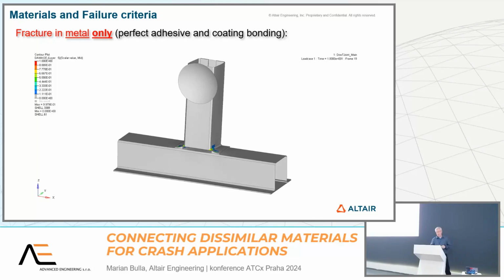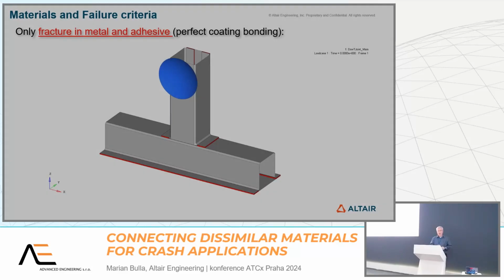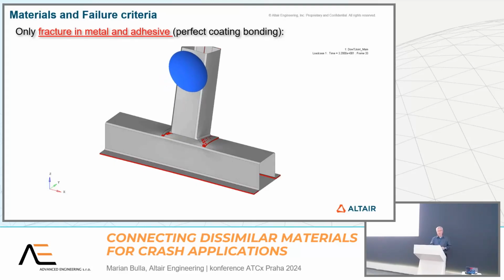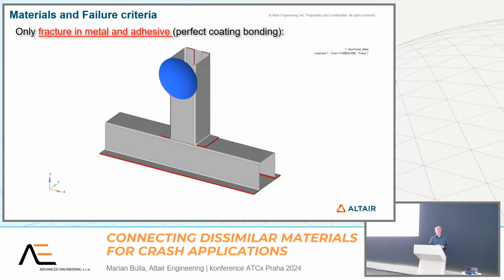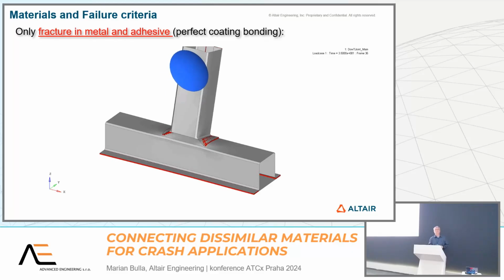So and now let's do the validations. First, fracture is applied only in the metal, not in adhesive nor in coating. And once we load, this is the virtual test, the FE simulation done here with Radioss. We see only fracture in the base material. Why? Because I applied it only for the metallic part, with perfect adhesive, perfect bonding, which is not the reality, but just for tests. Now I apply failure in addition to the metal also for the adhesive. And I see here my elements, which represent the cohesive zone elements for the adhesive, are disappearing, which is much closer to reality. But the painting, the coating, is still perfect.